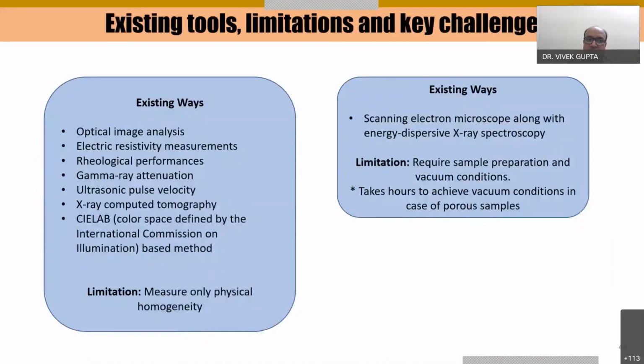So these are the existing ways, like optical image analysis and electrical resistivity measurements. You will see in different literature rheological performance, gamma ray attenuation, UPV, X-ray computed tomography, and so on. These are different methods which measure only the physical homogeneity. However, there are certain methods for chemical homogeneity also, like the scanning electron microscope, SEM images along with EDS, which we generally use for chemical homogeneity. But still, it requires sample preparation and vacuum conditions.